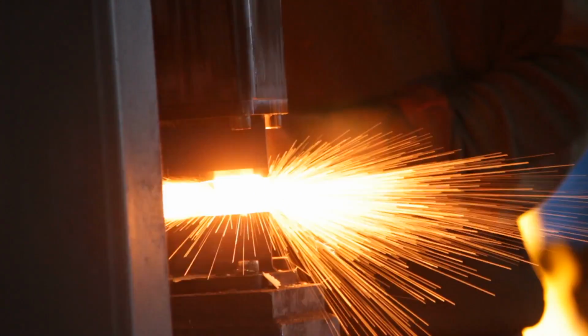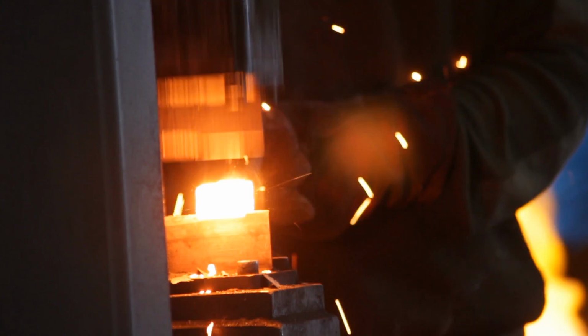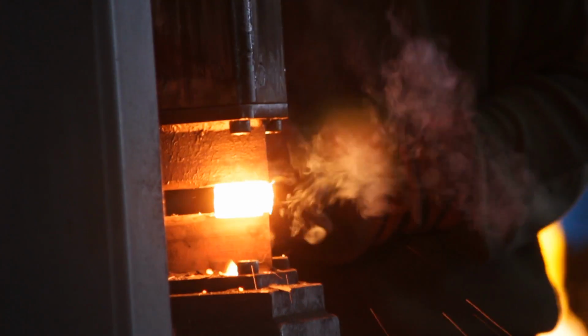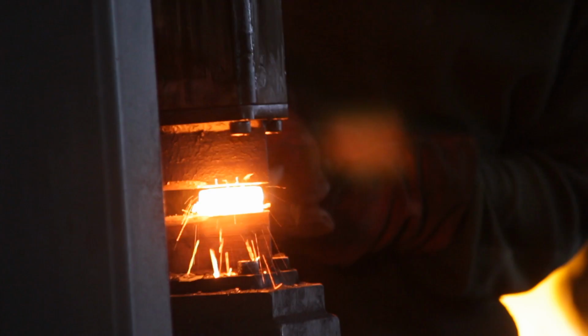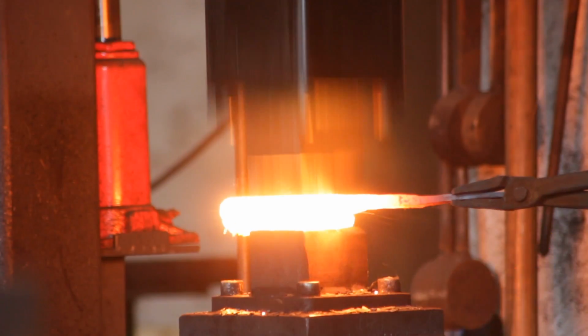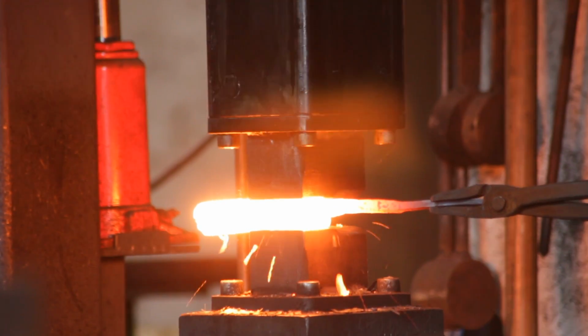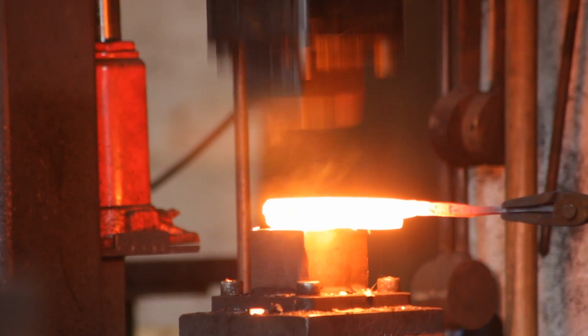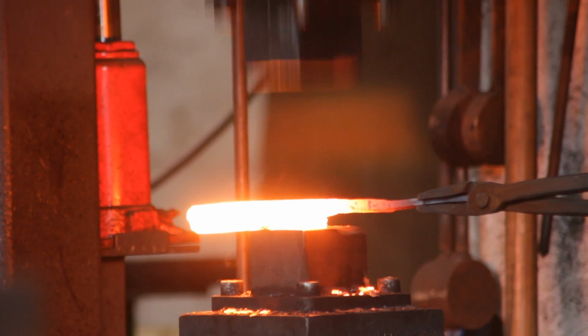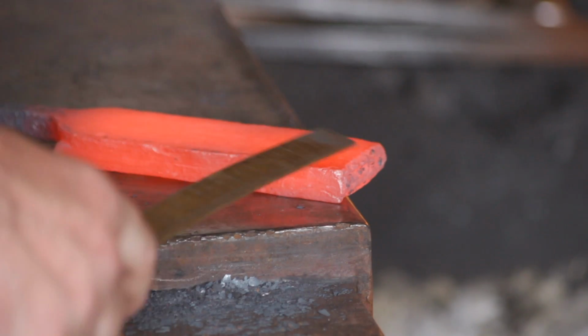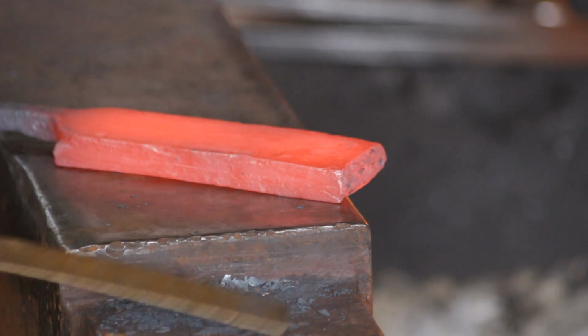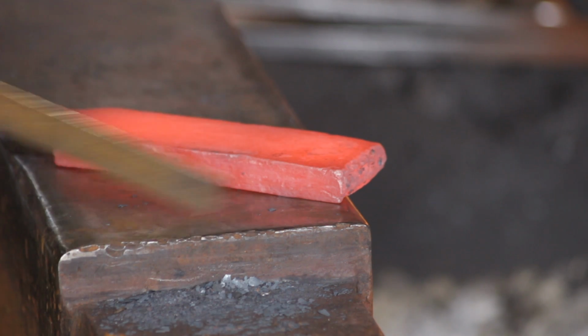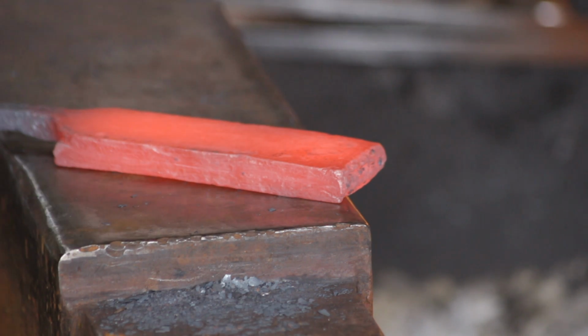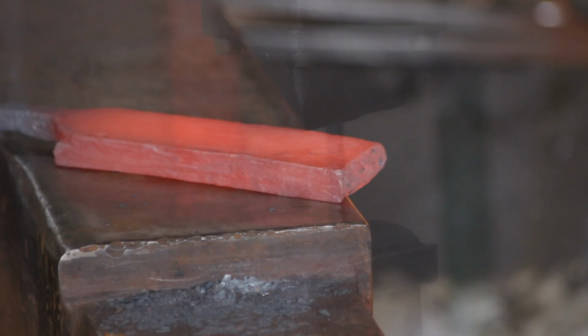So this is wrought iron, so you want a snowball heat with a molten surface. Not using any flux because wrought iron is pretty much self-fluxing anyway. And I tend to only flux carbon steels anyway. And I folded it twice in order to refine the grain of this iron. So you will notice you lose a fair amount of volume from doing this to wrought iron, and that's because you're pushing out the slag and impurities from the grain.